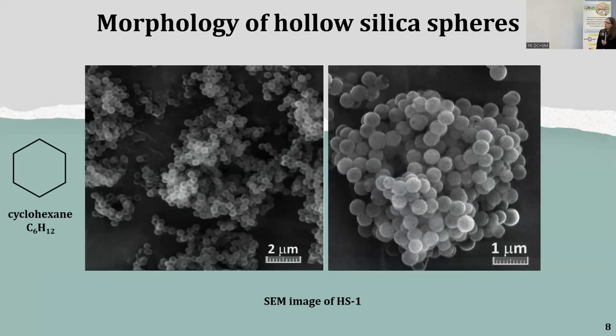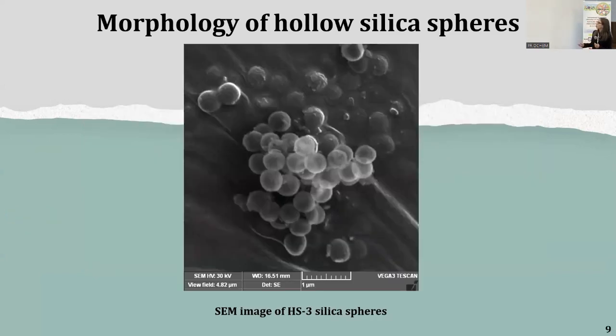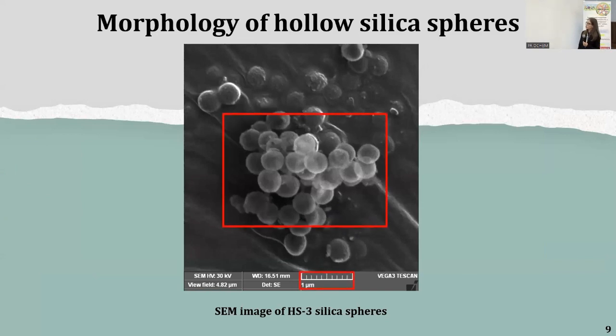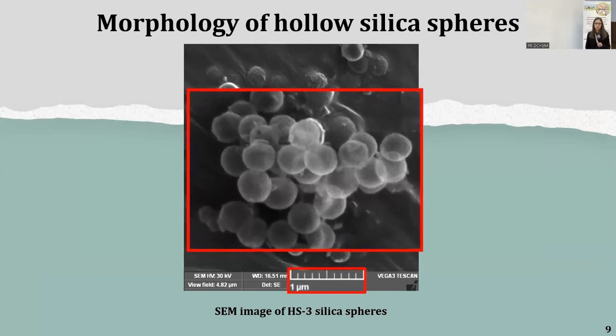The morphology of hollow silica spheres was analyzed by SEM analysis, and they show a very uniform particle size and a well-defined spherical shape when cyclohexane was used as a swelling agent. And in this SEM micrograph, you can see that the silica spheres are hollow.